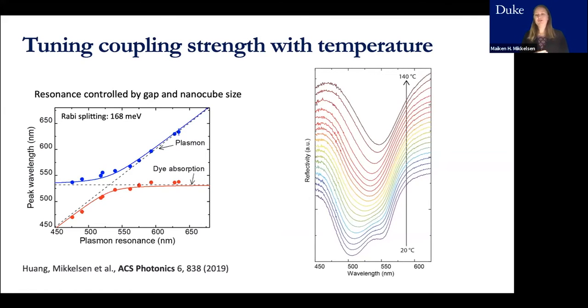And a way we found we could do that is actually by changing the temperature, because we use these polymer layers in the gap, and it turns out that these are actually sensitive to temperature. So they are slightly expanding and contracting with the temperature, water emerging and re-emerging into the structure. So you can see we go from a single dip here to this double peak, so we can really tune the strong coupling in real time.